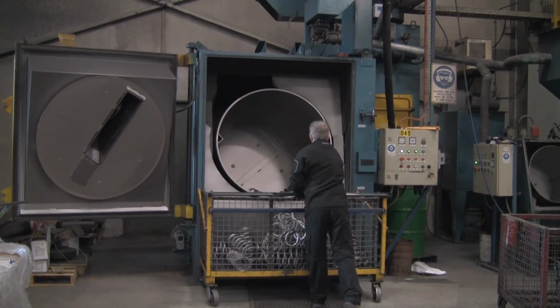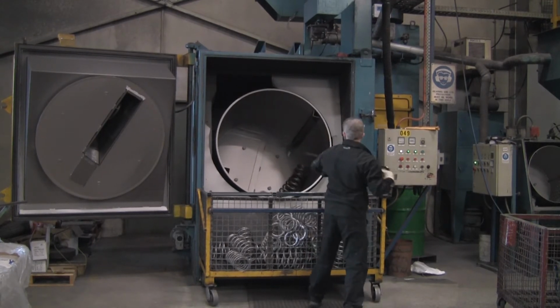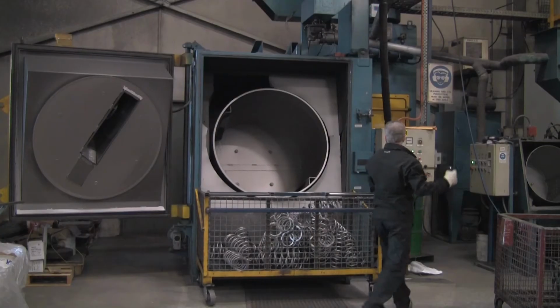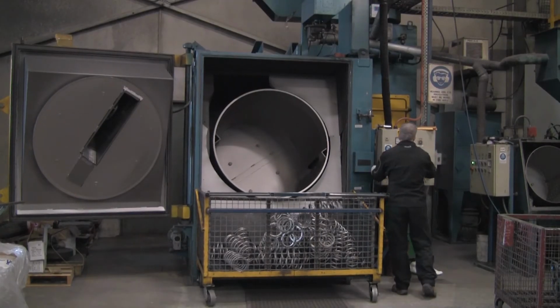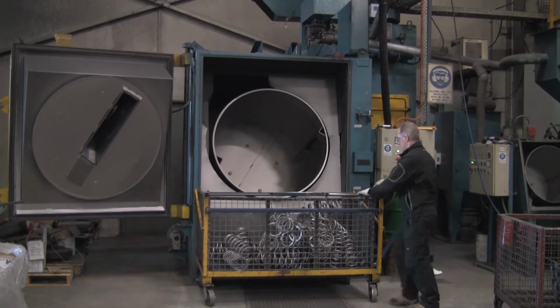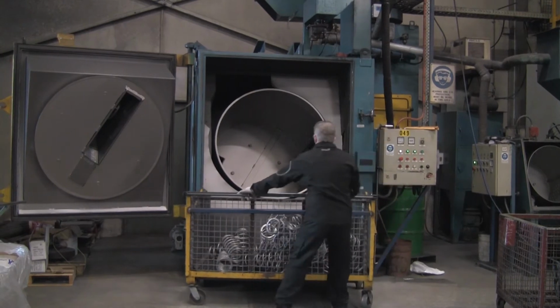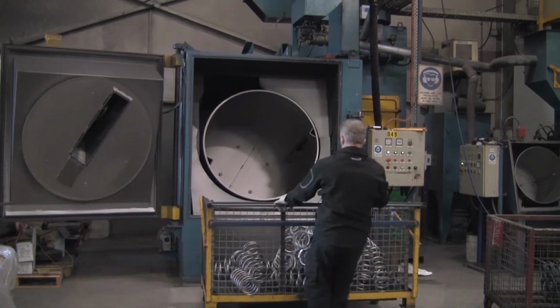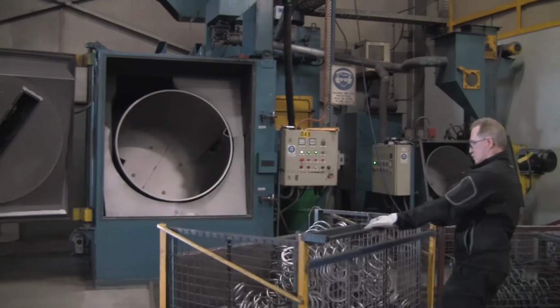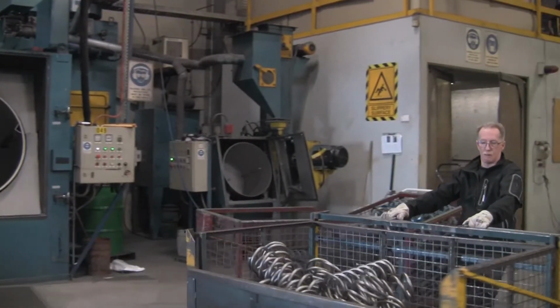Shot peening affects the coils in that it removes all unwanted particles from the surface and gives the coil a nice clean surface ready for powder coating. More importantly, the shot stress relieves the surface of the material, therefore removing any impurities that may possibly cause a problem with the coil later in life.